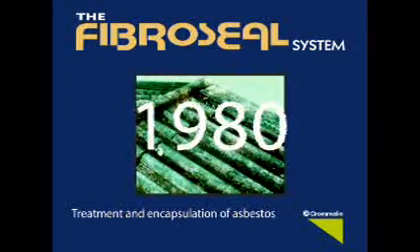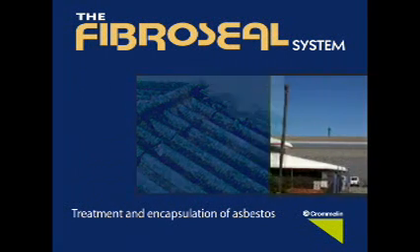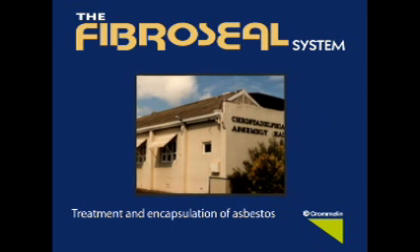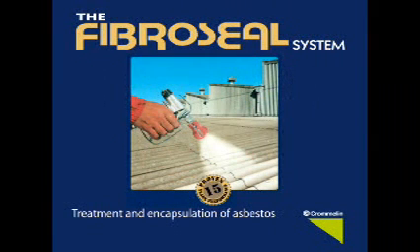In the 1980s, the use of asbestos was discontinued in the production of fibre-reinforced cement sheeting, but the ageing existing roofs continue to deteriorate. The traditional process for coating asbestos cement roofs was to firstly clean the roof with high-pressure water to remove all lichen and loose asbestos fibre. This procedure, however, was banned on health grounds, creating a need for a system which could be applied straight to the degraded asbestos without disturbing the surface.